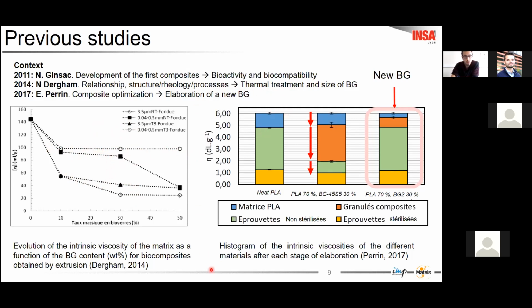In this other study made by Eloise, we can see a histogram showing the evolution of the intrinsic viscosity for PLA with 30% of bioglass, type 45S5, and for a new bioglass developed in the context of this thesis.